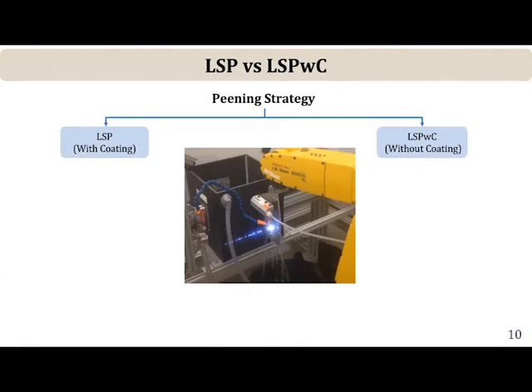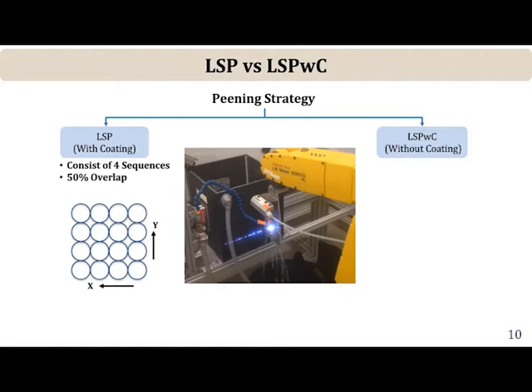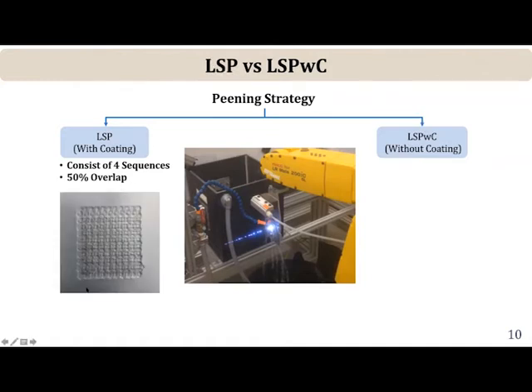So just comparing the two. When you do this without a coating, Anurag has done this with and without the coating. To create a patch like this, you have to use 4 overlap sequences, sometimes many more, depending on the degree of overlap. So each time we've got to change the tape, right? And this is the net effect that you get from laser peening with the tape. When you use the coating, you don't have any surface melting. It's a purely mechanical effect, and you get fairly high compressive residual stresses. And the degree of surface roughening is also low.